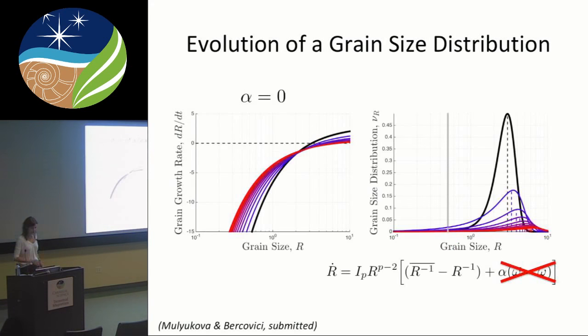All right. So this is just to convince you that some of what we learned from two grains is extendable to this more realistic system of an ensemble of grains. An example again, if alpha is 0, this is what happens. You're seeing grain size on the x-axis in both of these plots. This is what's happening to the grain growth rate. When it's negative, it means the grain is shrinking. When it's positive, it's growing. And here is the evolution of the grain size distribution itself.